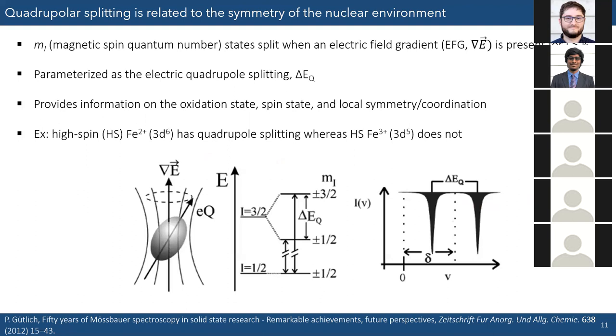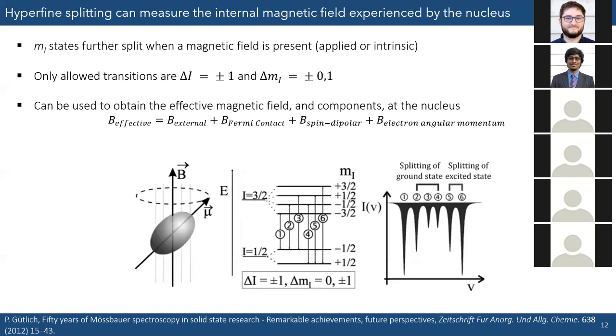Okay. So then the last main piece of information that can be taken from Mössbauer is this hyperfine splitting. And this is only present whenever there is some sort of magnetic field present, be it an internal local magnetic field that's being created by nearby atoms, or actually just an applied magnetic field. And so now if we look again at our energy diagram, all of those m sub I states I had previously talked about were doubly degenerate, having both their positive and negative components. But now in the presence of this magnetic field, these are going to start being split.